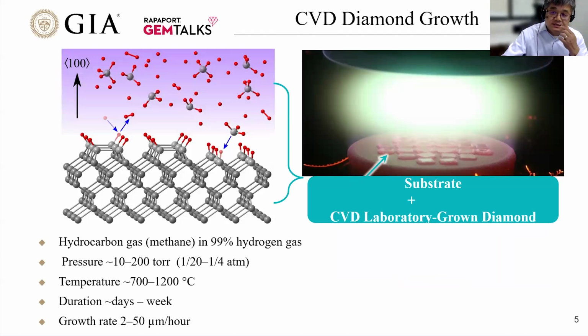For CVD technology, it is basically at vacuum condition. Methane gas is introduced, but dominated by hydrogen gas. Only about 1% of the gas introduced to the vacuum is methane. Methane is CH4, with carbon as the source for the diamond. Microwave is used to heat the gas to a very, very high temperature that generates a plasma. Here you see a plasma ball. In the plasma, the temperature is so high that it ionizes most of the molecules. The methane will be ionized and the hydrogen gas will be ionized.